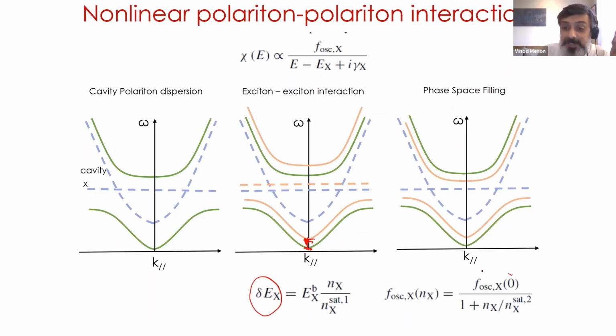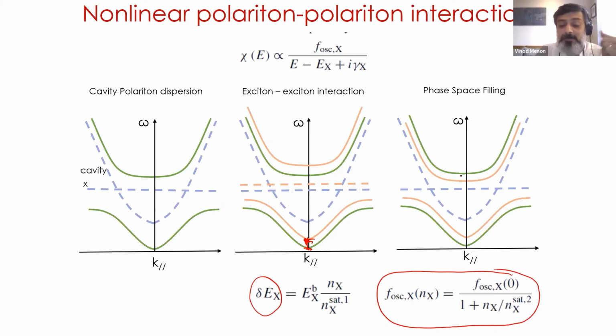Of course, there is another effect that can also happen, and as it turns out, what we have figured out is that in the 2D TMDs, this is the effect that seems to dominate, where as I increase the exciton carriers, because the excitons start seeing each other, I start getting a phase space filling effect, and so my Rabi splitting starts decreasing.